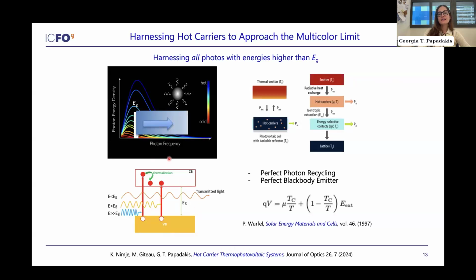So what we thought is something that has already been considered in the case of solar PVs. Solar PVs have been investigated in terms of hot carriers, and here we do the same for TPVs. A standard PV will be most happy if it receives energy from the sun that is very narrow band, and a TPV the same. But if I extract more photons and I create a very broadband spectrum, I have an emitter that emits photons from the bandgap all the way to infinity, and I can extract these photons before I let them thermalize, which is what this diagram shows, then I can reach the endo-reversible limit.